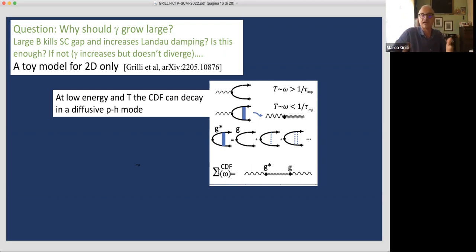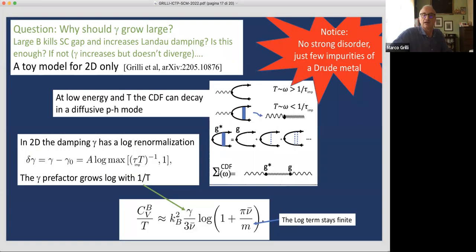The charge density fluctuation, again, decays into a particle-hole pair, but at low frequency and low temperature, it decays into diffusing particle-hole pairs. Notice, as I said, that you don't need to have strong disorder, but just a few impurities is enough, because all that matters is that you have, at small temperature and small frequency, a finite impurity scattering rate. And if you dress the charge density fluctuation with this diffusive pole, then you find that in two dimensions this Landau damping parameter diverges logarithmically with T. So when you decrease T, you have a diverging Landau damping.